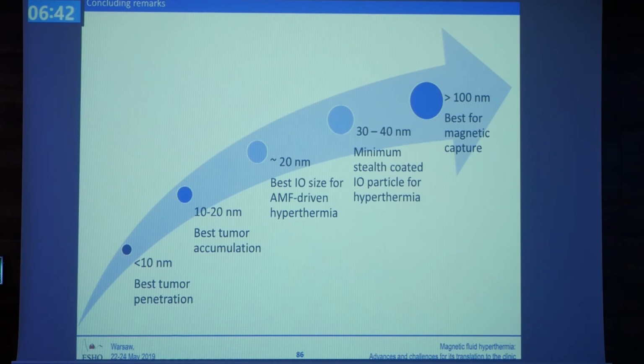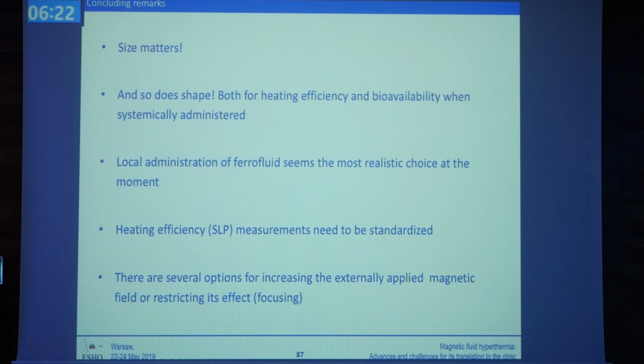But what we need are iron oxide particles which are stealth. They're not picked up by our reticuloendothelial system to be excreted, and we want to keep them in the ferromagnetic regime, not in the superparamagnetic, just to make them heat a lot more because of this size. And not only size matters, but I have shown that also for systemic application in clinical practice, the shape would matter, because they circulate in a different way inside our blood vessels, but also the heating efficiency changes. The more anisotropic the nanoparticles become, the more they heat.